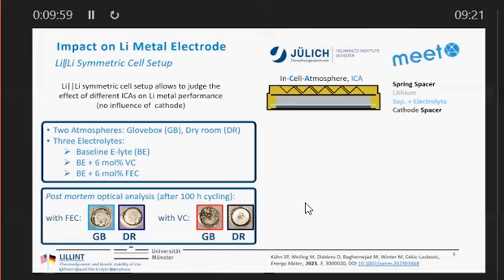We used a base electrolyte, which is a carbonate-based electrolyte, and then we used VC and FEC, vinylene carbonate and fluoroethylene carbonate. So, let's say, the two typical additives in lithium-ion batteries. And then we did cycling. Already when we open the coin cell, we see that there is a difference in the deposits. The coin cells made with VC and FEC are different.